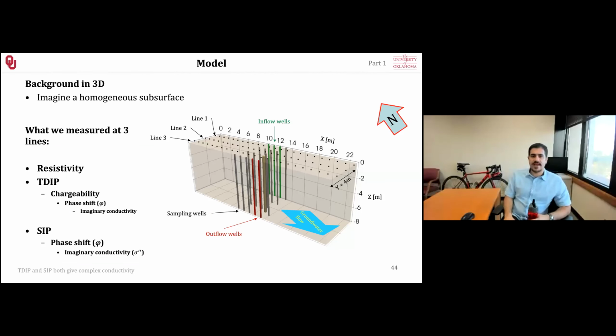What we did here, we had 3 lines that we measured on electrical resistivity and time domain IP, and 2 lines for spectral IP. We measured the chargeability, that we were able to convert into phase shift and then take out imaginary conductivity out of that for a time domain signal, because we knew the frequency that the IRIS instrument was working, and we easily could compare it to the SIP measurements.